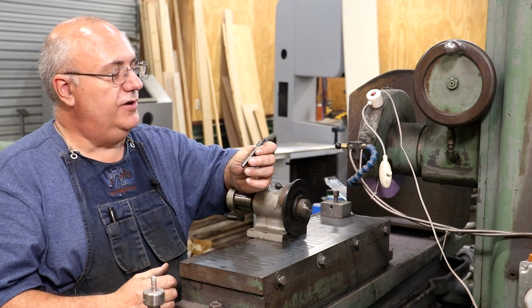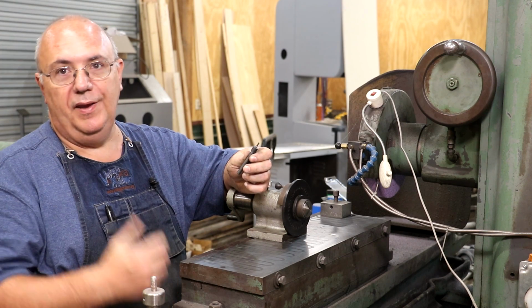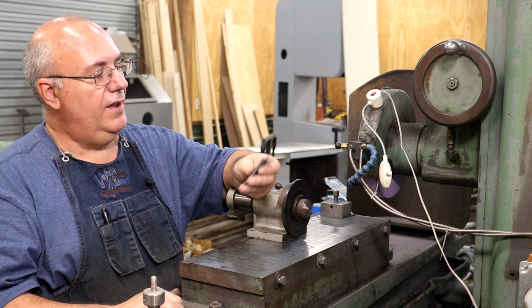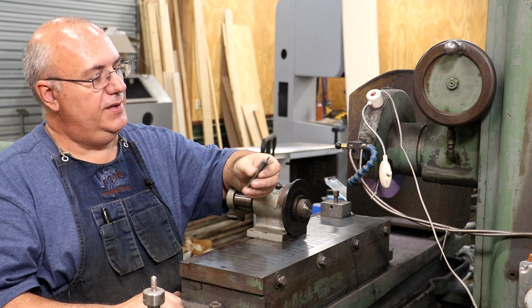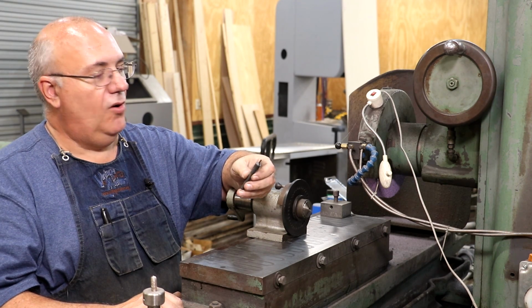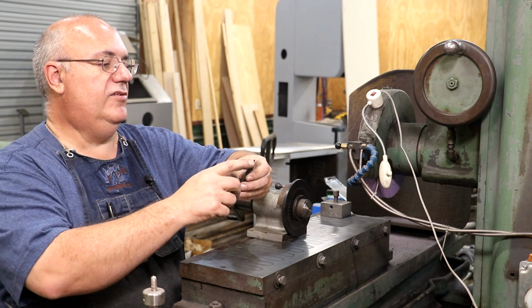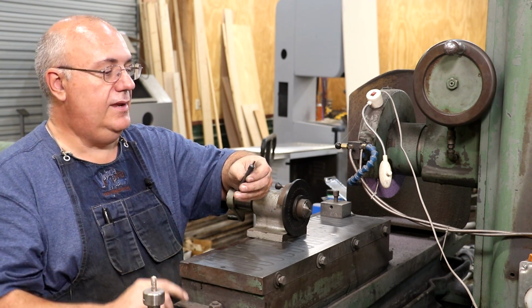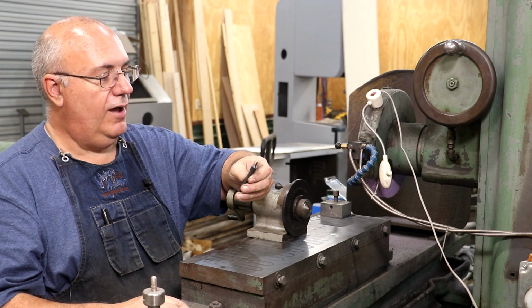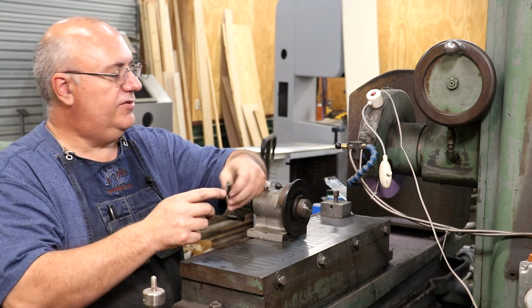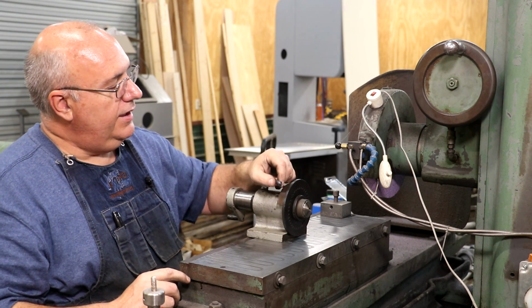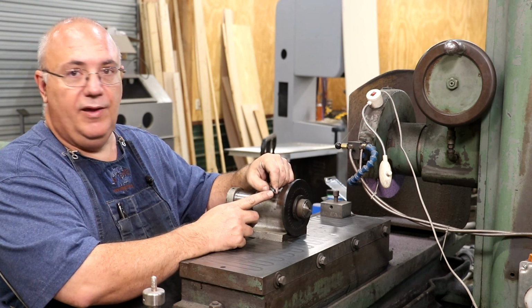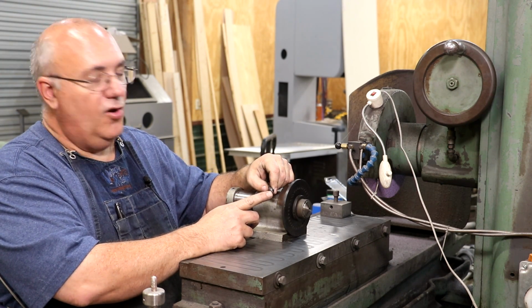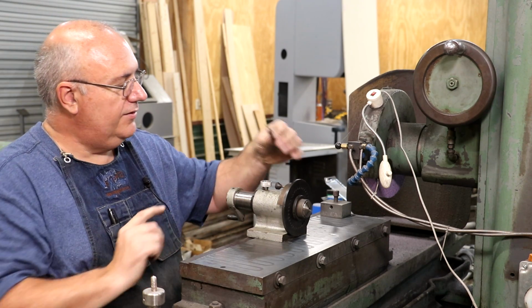Well, I finished the heat treat on this, and I didn't really show it. All I did was pull it out of the oven after it had cooled down, but we got our part here. It has been completely heat treated. It's been hardened and tempered. Again, this bottom end down here, the pin should be around 48 Rockwell, somewhere in that ballpark. The rest of it is still fairly soft. And I turned this purposely about 10 thousandths oversized, and I needed to get it down to the final size.